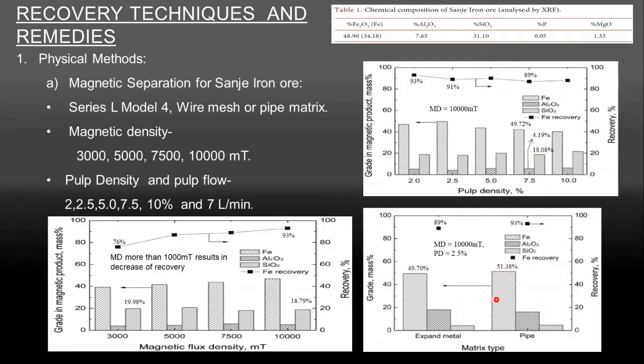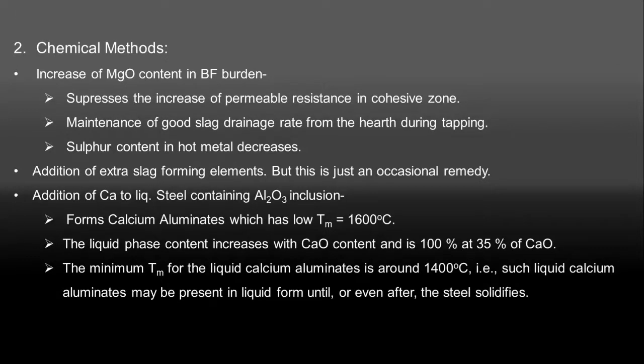And coming to type of matrix, expanded metal, which is wire mesh, has 89% recovery with 49.70% of iron content, and pipe metal has 93.93% of recovery with 51.38% of iron. Here are some chemical methods to decrease the effect of alumina in BF iron making route.